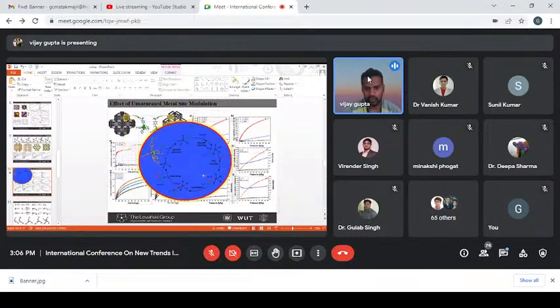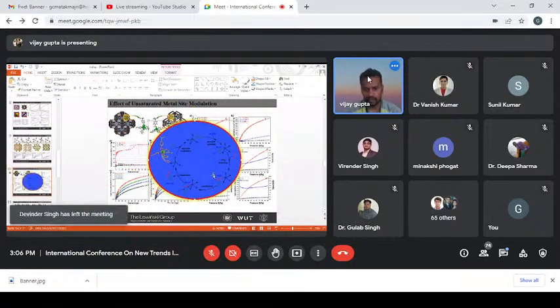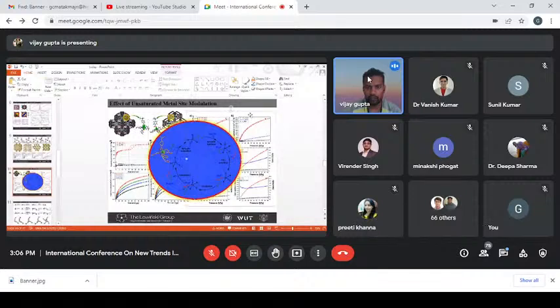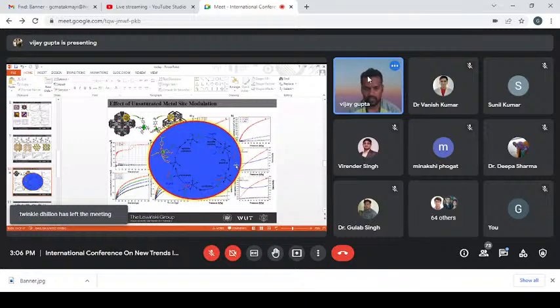And the other thing is how this unsaturated metal site helps in CO2 activation or small molecule activation and CO2 utilization. So we use strained molecules to interact with this CO2 molecule. Basically, we use epoxides, and this unsaturated metal site helps in the epoxide activation, and the CO2 adsorbed in the framework adds up into this molecule, making cyclic carbonates, which are industrially useful molecules, made from this waste CO2.